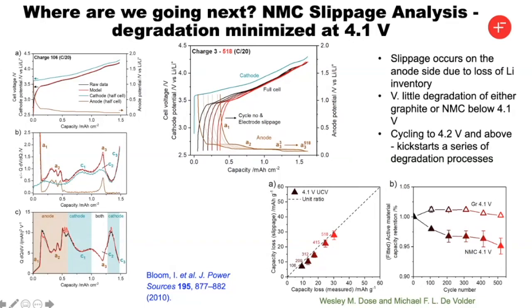And so in work of Wesley Dose and Michael De Volder, we've been trying to really pull apart where the degradation process is occurring, and using the sort of approaches of slippage pioneered by the Argonne group, what we're doing is taking full cell data, decomposing it based on half cell voltage profiles obtained for the anode and the cathode. And what that allows you to do, instead of looking at the DV/DQ, you look at the DQ/DV, which allows you to add in a linear fashion the components that come from the anode and the cathode. And when you do that, you can see that the capacity loss is largely associated with a slippage on the anode.